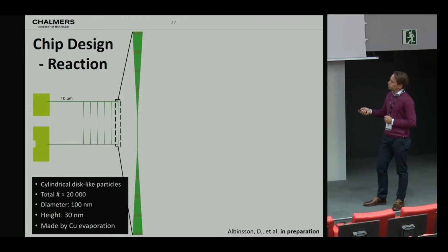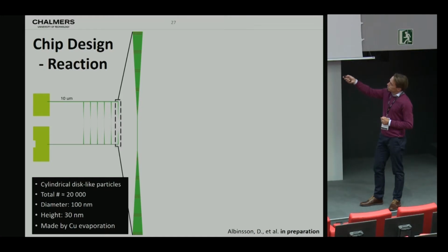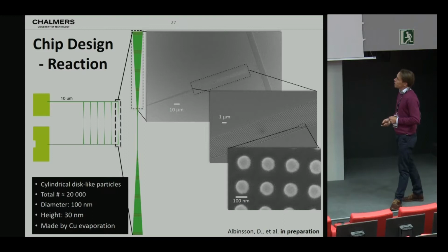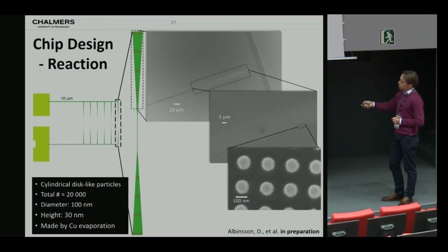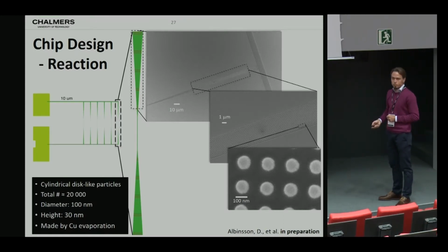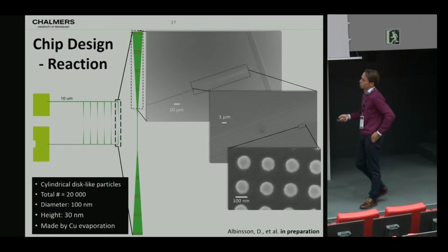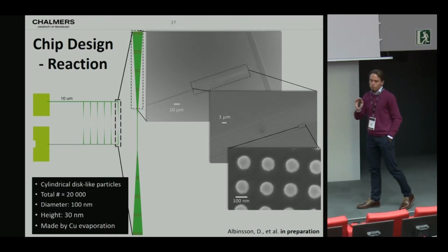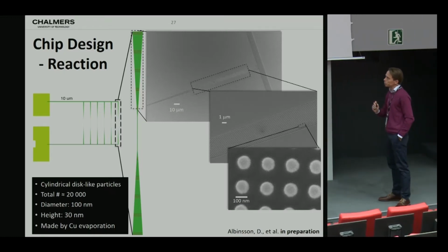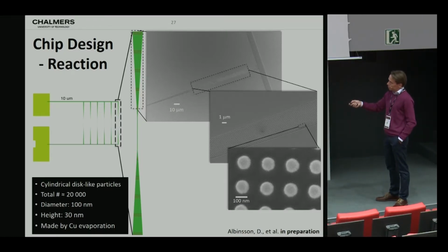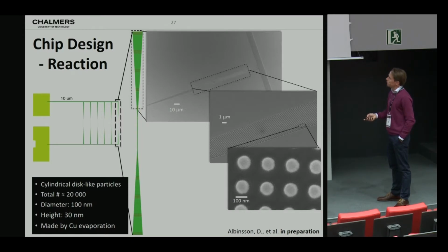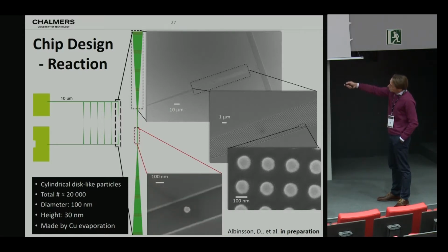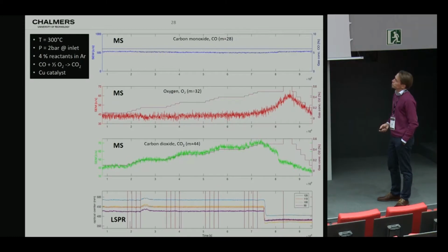But we wanted to be on the safe side and started out by decorating not just the nanochannel, but also this funnel here with an array of nanoparticles that would look like this, so that we have about 20,000 particles in our system. But I can tell you that already now we know that we can reduce that down to 200. But I will not show that today. They have 100 nanometer diameter, 30 nanometer thick, and made from copper. And then in the nanochannel here, we have the individual particles which are separated such that we can look at them individually by dark field scattering spectroscopy.